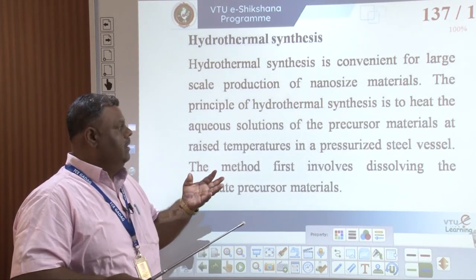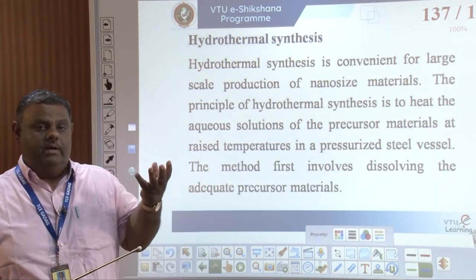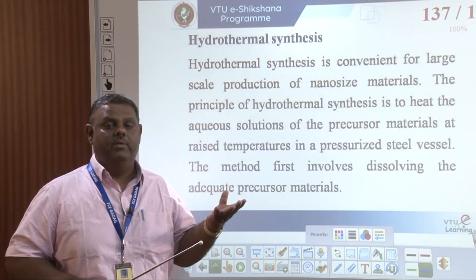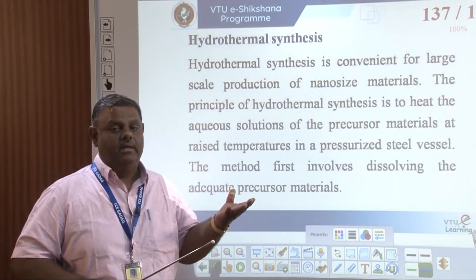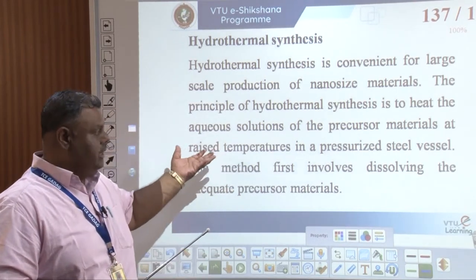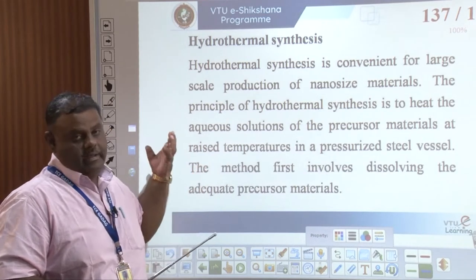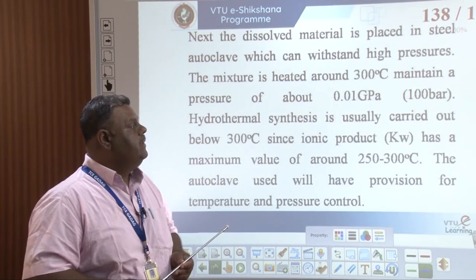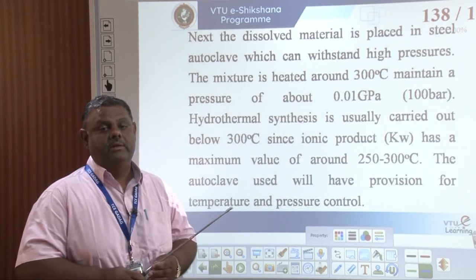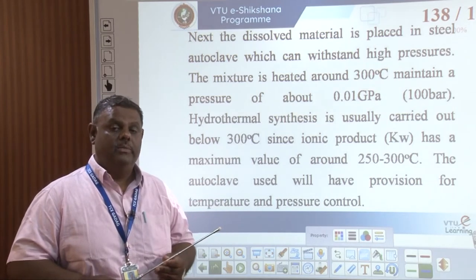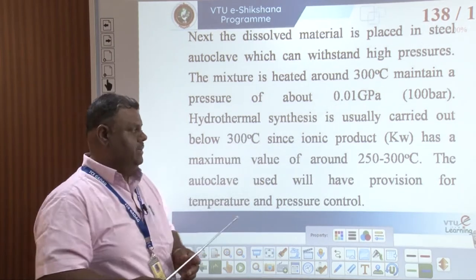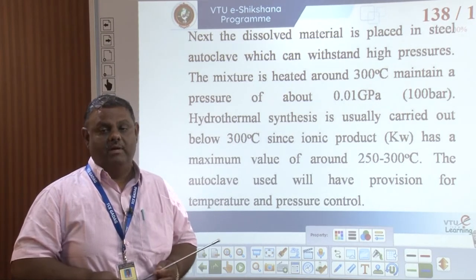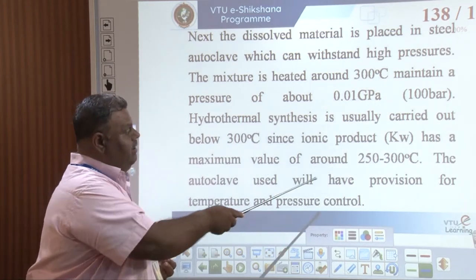The temperature is around 300°C and the pressure should be kept around 100 bar. The reason for maintaining around 300°C is that the maximum ionic product of water is available in the range of 250 to 300°C. Therefore, well below 300°C, the mixture is heated at a pressure of around 100 bar, causing the precursor to interact with water and become hydrated.